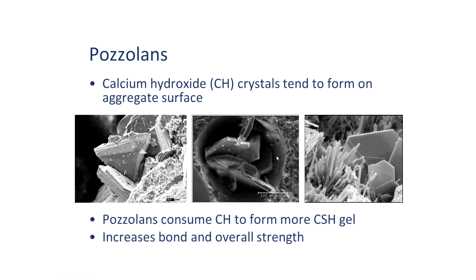And these like to form on the surface of the aggregates. So they kind of act like bond breakers that prevent the cement paste from bonding really well to your aggregate, so you get weaker concrete. Well, what our pozzolans do is they consume it, they make it go away, they create more gel, and now we get a better bond, and that's where this better strength comes from.